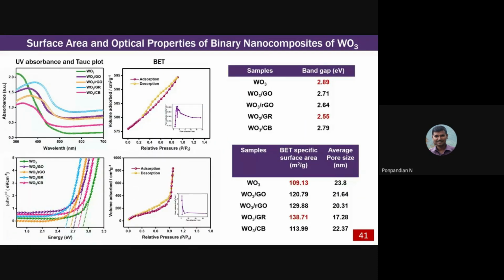Now you can see the surface area, and how the band gap can be changing for the different morphologies of this tungsten oxide. For example, pure tungsten oxide is 2.89. For tungsten oxide with graphene oxide, 2.71. With reduced graphene oxide, you get 2.64. Like that, you can see the band gap is tuned. Like that, at the bottom you can see the surface area can also be tuned based on the different morphology and different tungsten oxide compounds.